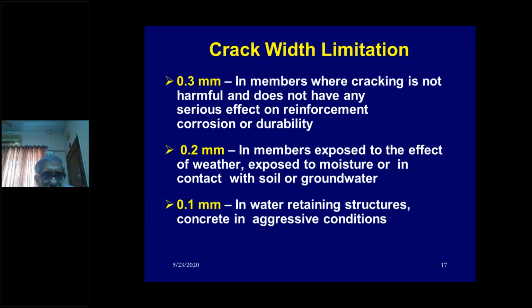If you see the IS 456, it recommends crack width limitations, from 0.3 mm to 0.1 mm. The 0.1 mm is for water retaining structures, concrete in aggressive conditions. 0.2 mm is for members exposed to the effect of weather, exposed to moisture, or in contact with the soil and groundwater. And 0.3 refers to structural members where cracking is not harmful and does not have any serious effect on reinforcement corrosion or durability. So these are the various crack limitations.